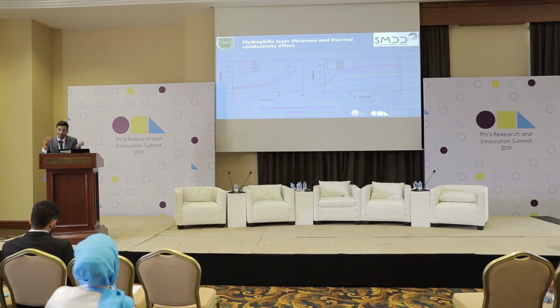But then I started thinking, because when you open a venue of research, there are huge doors open for you. So you can explore, and you are the initiator of the idea. And we thought about doing some mathematical modeling to predict the membrane performance. And I found out that the hydrophilic layer has a significant effect on the membrane performance. In the beginning of my career, in the first papers I published, I was saying that the hydrophilic layer does not have any resistance to the mass flux. But when I did the mathematical modeling, I found no, it does contribute, especially with the thermal conductivity.